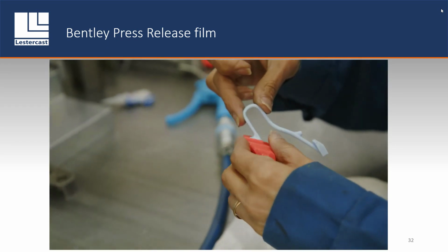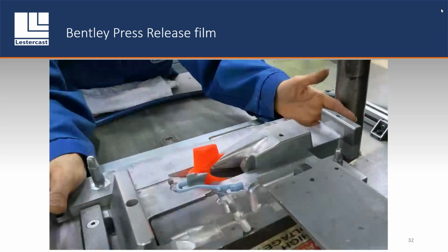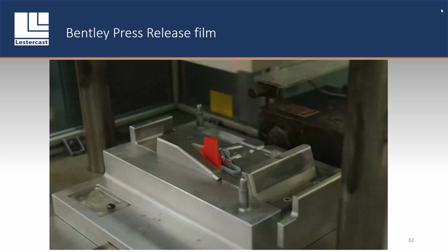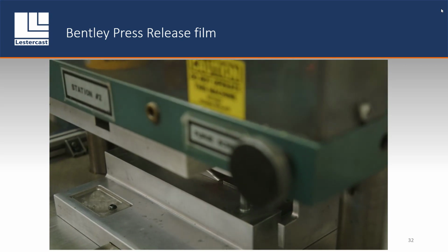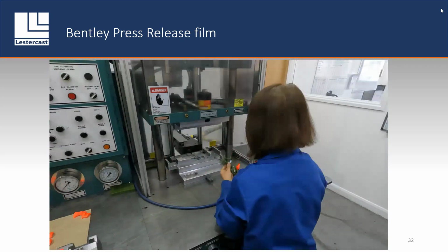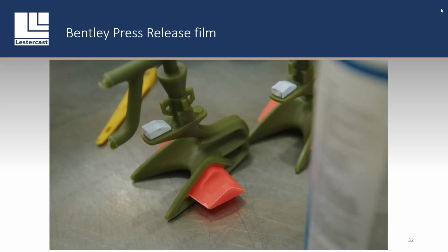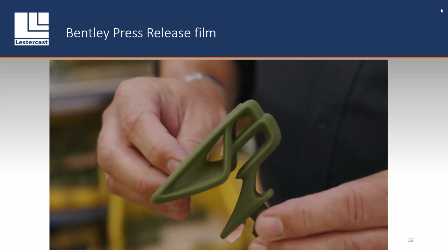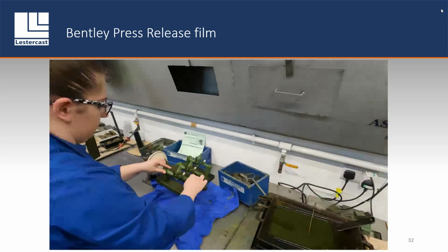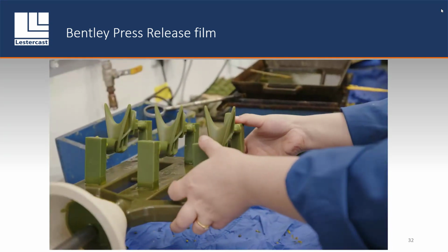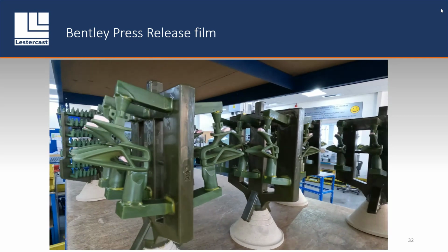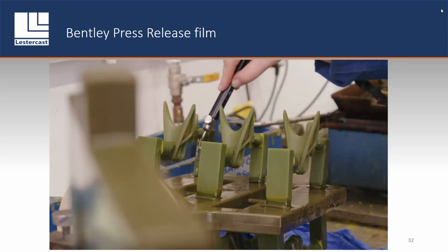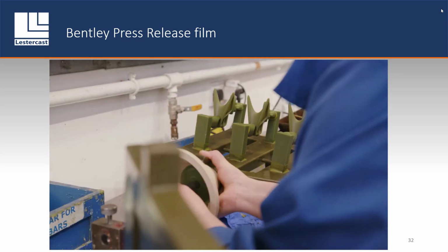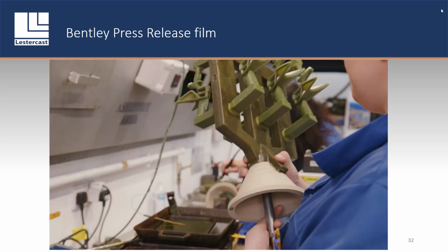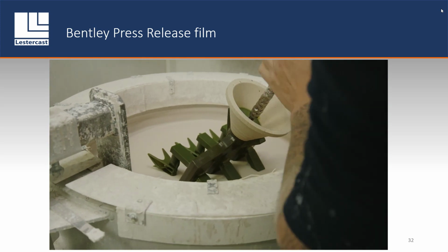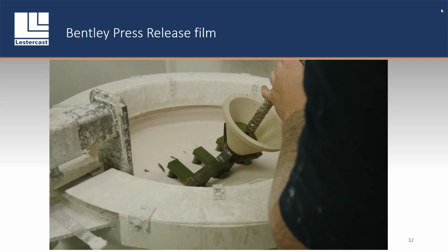So here you see the core assembly process that Russell's referred to, wax injection process. We form part of the feed technique in the die, so every wax pattern also produces its own feed and feed bar to aid the assembly. We then assemble onto the wax trees. We have a small flame tool for trimming off and putting some wax fillet into sharp corners, all to aid the shelling process. Here you see us going into the prime bath.